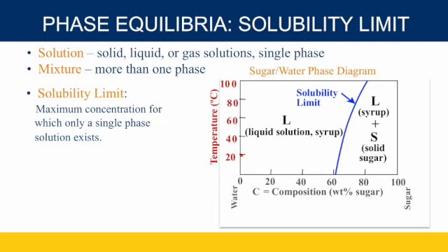if I heat a material at 20 degrees, so this would be room temperature, and I add sugar, this graph shows me that I can add about 65, 63% sugar to water, and I will get a single phase. That single phase is listed by liquid solution. You'll always see this on the phase diagrams. You'll have either a Greek letter or a normal letter that tells you the number of phases. Okay, so if I stay less than 63 weight percent sugar, I will have a single phase of a sugar water, a sweet, syrupy material.